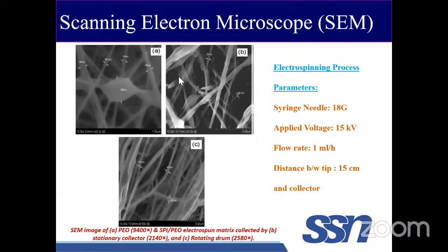So this is an SEM image of the prepared nanofibers. This is the pure PEO, right? This is with a stationary collector. This is with a drum collector. As you can clearly see, the fiber roughness is quite high in the case of the stationary collector than the drum collector. Here it is a smooth surface. Here it has a rough surface, where you can clearly see the twists and turns.